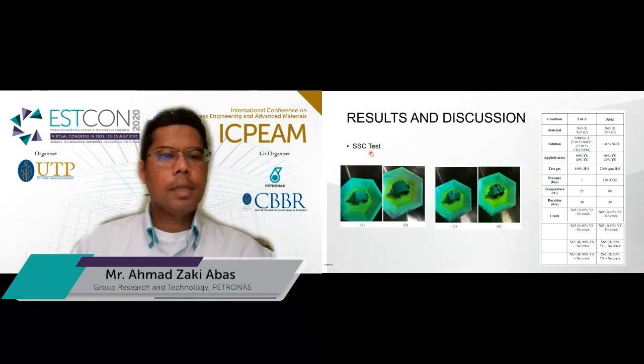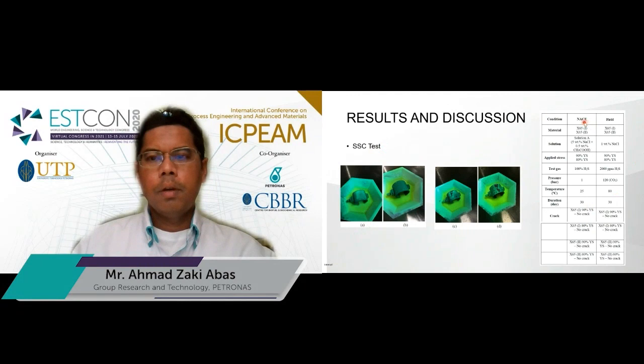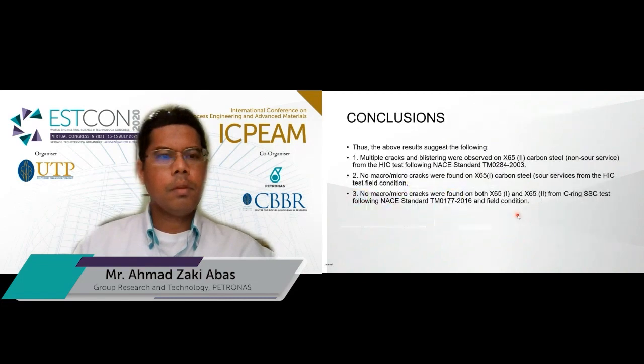And for the sulfide stress cracking, for the NACE and the field condition, there are no cracks for all samples. Conclusion: the above results suggest that multiple cracks happened on the non-sour service carbon steel for the HIC test following the NACE standard, and no cracks were found for the sour service material for the HIC field test condition. And for the SSC ring test, there is no crack for both sour service and non-sour service pipelines for both the NACE standard and also the field condition.